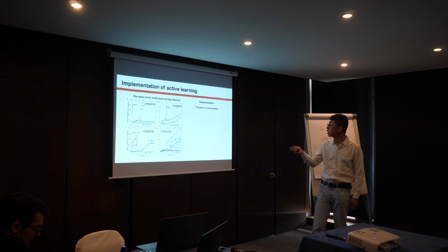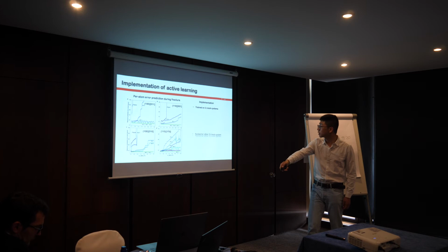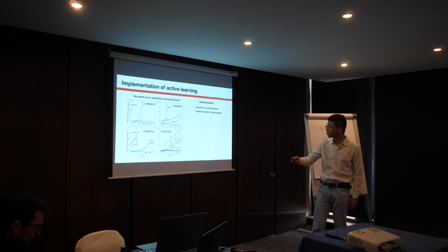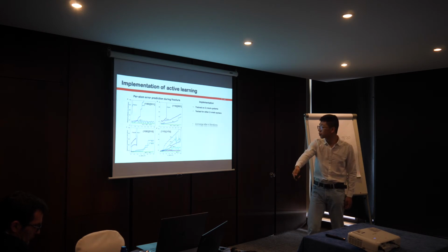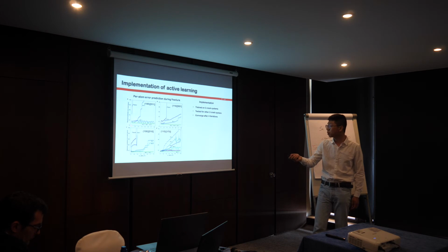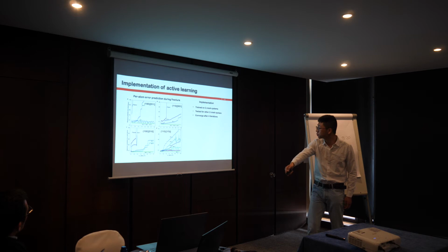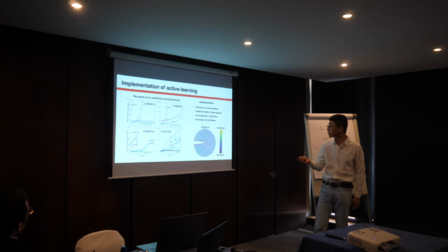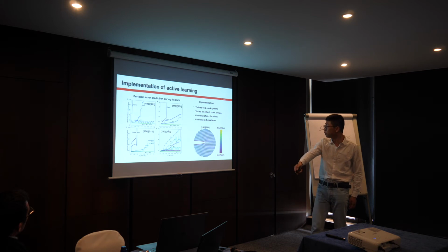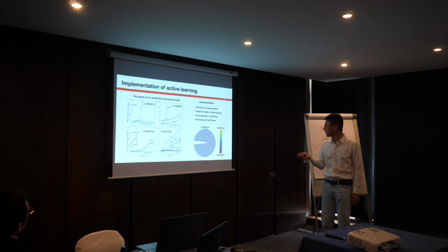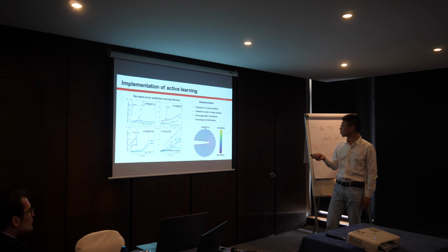So we trained the system with active learning on these two crack systems, and tested on these two crack systems. We can see that in 4 iterations, the average error goes down and converges to less than 8 meV. Here the video shows that during the entire cleavage process, we don't see any atoms with error above 8 meV per atom.